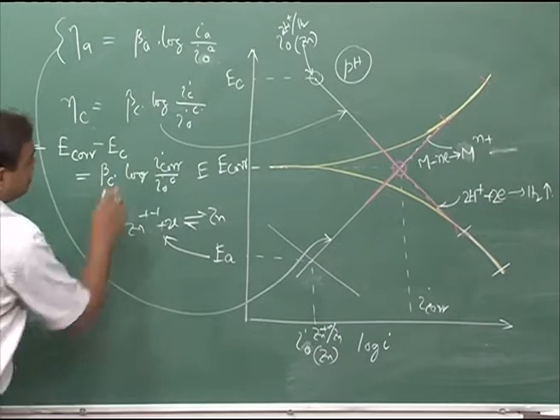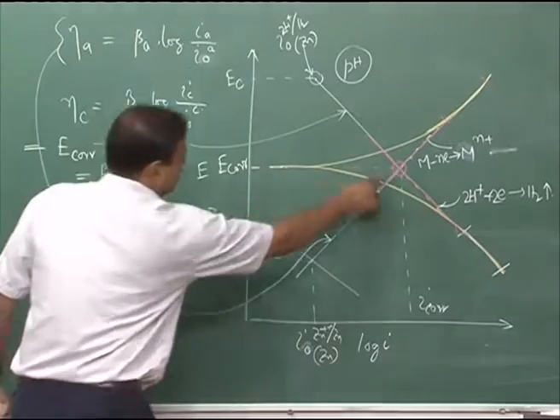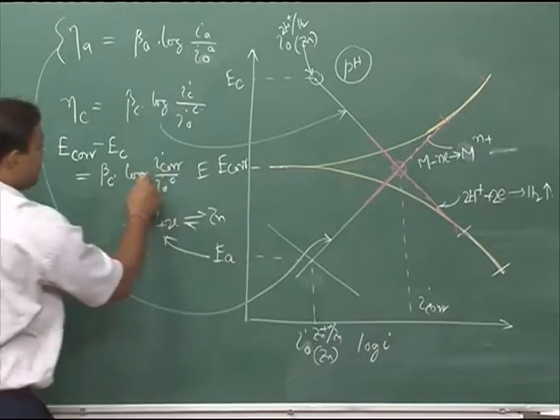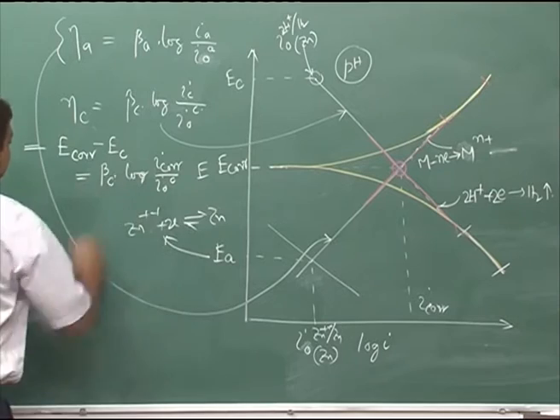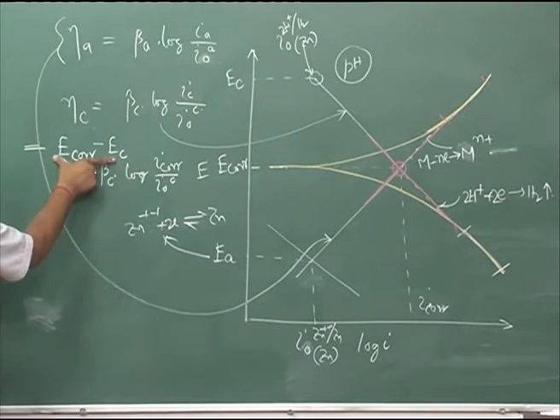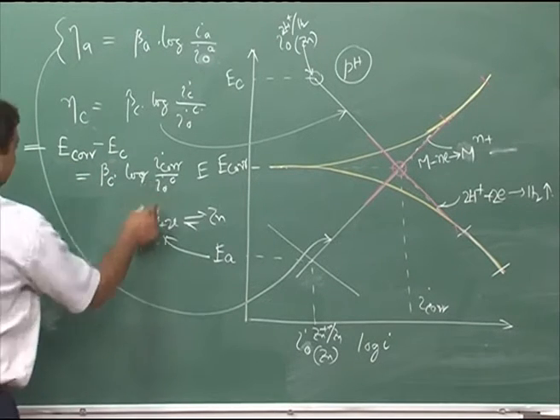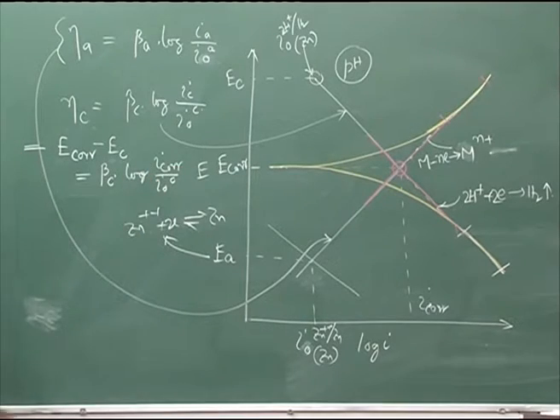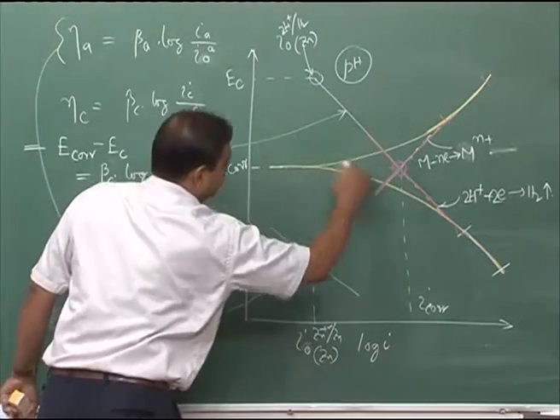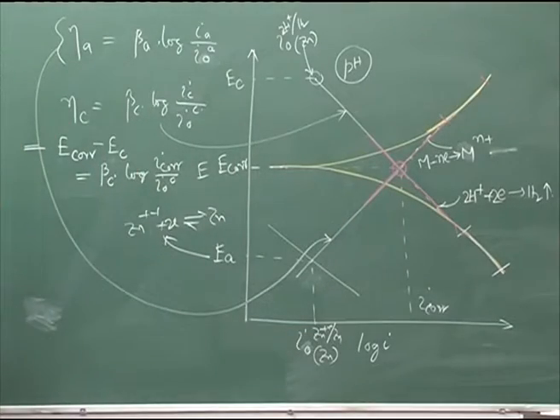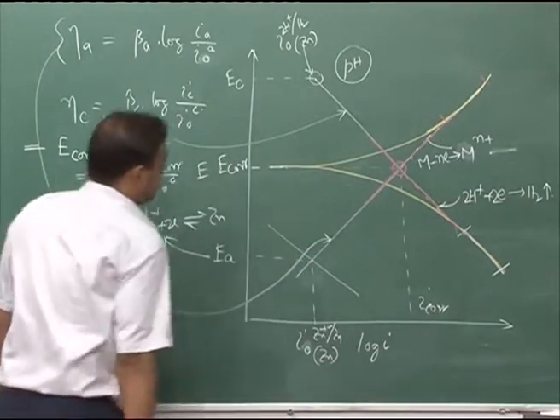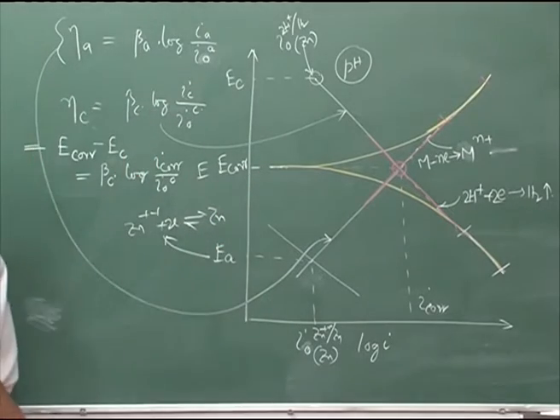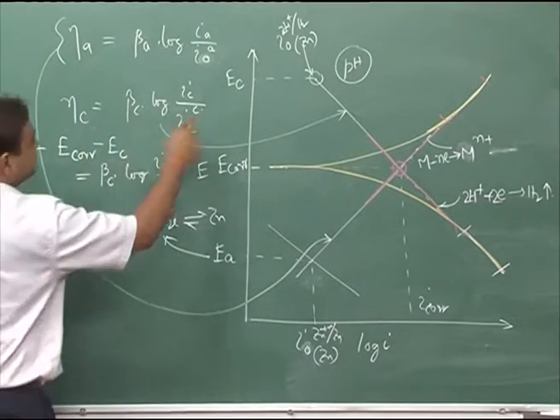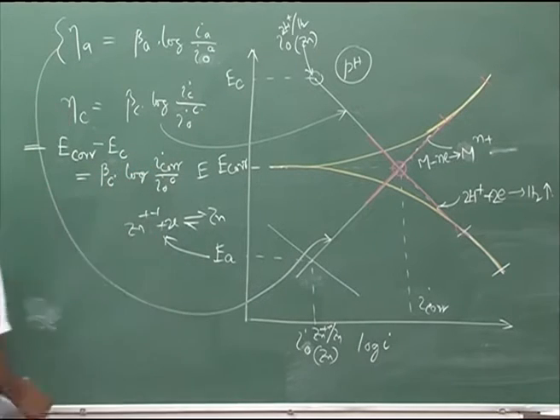Now, I cor is also falling on the line. I can put that I cor in that equation instead of Ic at this point, and this is my over voltage, cathodic over voltage. Beta c we can calculate for that system. I0, if we know, we can also find out what is I cor. So, one way is if we can have this Tafel slope and find out from the graph, or other way around, if we find out what is the corrosion potential, and at that time if we know the pH value, we can find out what is E cor.